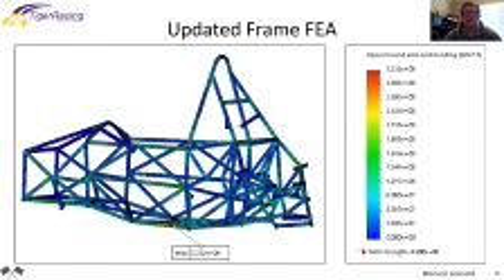A simulation was run to determine if the frame would fail under a 40G crash scenario. Using the weights of the battery housing and motor with attachments, it was found that the peak stress was 323 megapascals, which is less than the yield strength of chromoly 4130 steel of 460 megapascals.